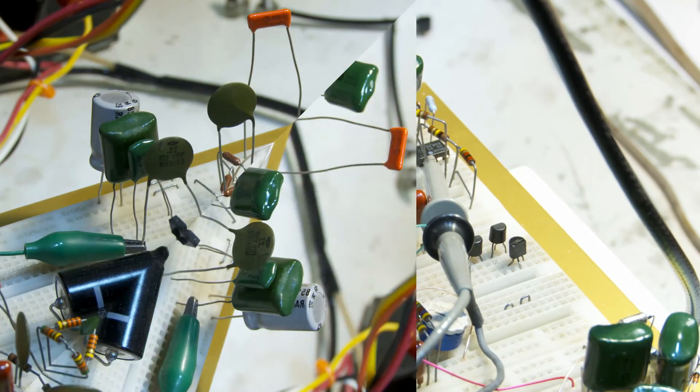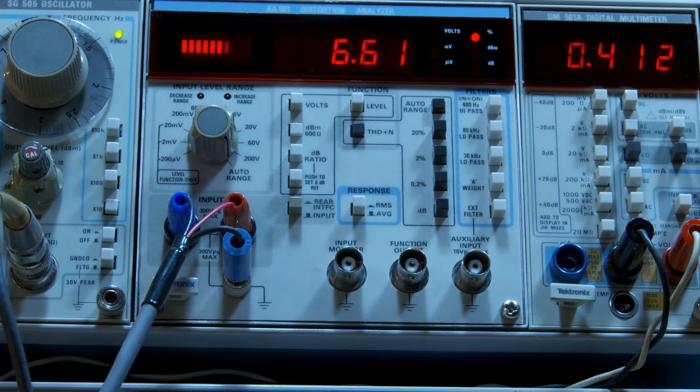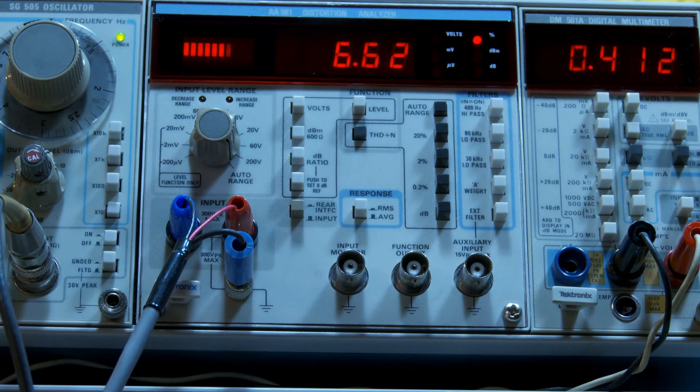Now let's put our ceramic disc capacitors back in. Oh my, distortion is up over 6.5% with the ceramic capacitors.